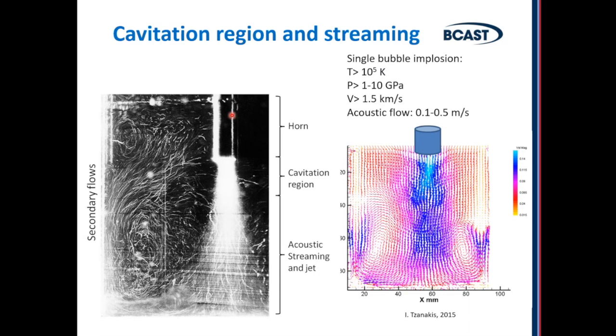If we talk about specific areas, we usually talk about the cavitation region, which is directly underneath the source of vibrations. It's usually roughly the size of the diameter of the probe or sonotrode, sometimes a little bit larger. And then there is a downward flow which recirculates like that. These are experimental observations, PIV measurements, particle image velocimetry measurements of the velocities. And velocities in this area of the secondary flows are in the range of centimeters per second.